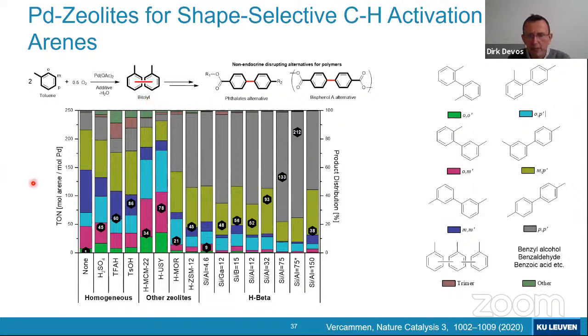Now let's look at the reaction data. In many of these plots we have the turnover number, so the number of moles of arene that we convert per mole of palladium, at the left side. And then the product distribution is shown on the other axis. So the black diamonds typically are the activity. And then we see that indeed, for instance, the palladium in combination with paratoluene sulfonic acid gives quite good turnover numbers. But what you essentially make is a mix of all possible isomers. And the isomers are labeled here in all these colors.